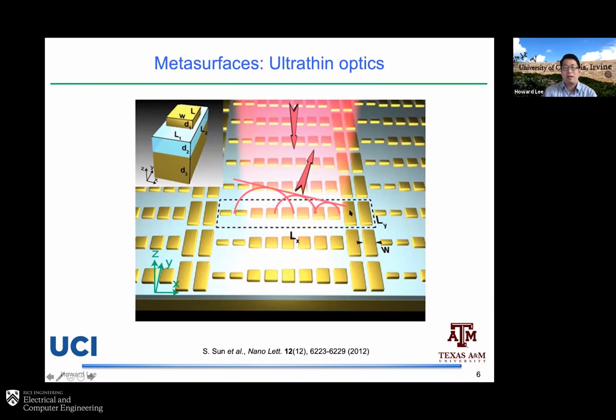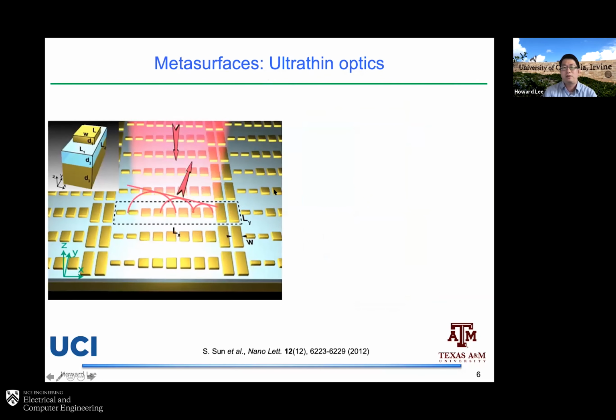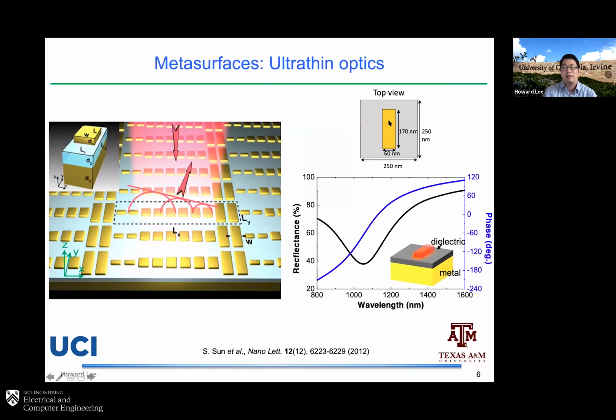So this is some of the idea of metasurface, basically using this kind of resonator antenna. For example, a simple metallic bar, you can have a metallic resonance. And because you have a metallic resonance here, if you look at the optical phase, you find you can change the phase by 2 pi across this resonance. So that means using one antenna, you can change the amplitude and phase, and that's why you can engineer the structure so that you can control the phase precisely to make an artificial phase front. This is exactly what the metasurface does.